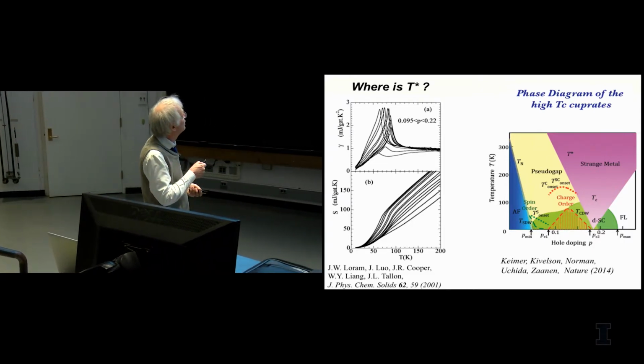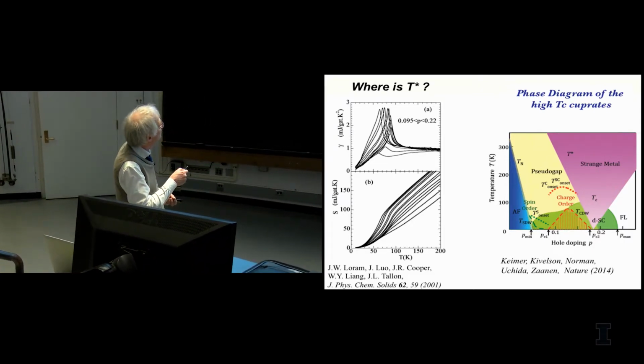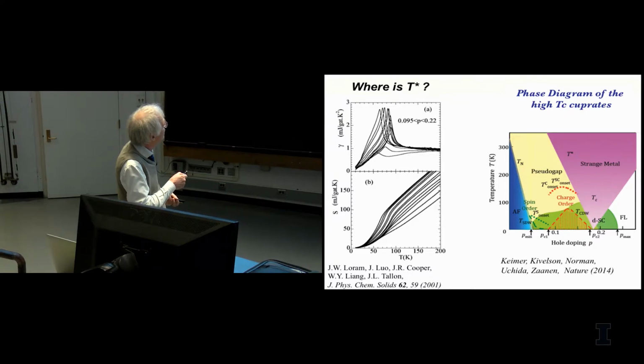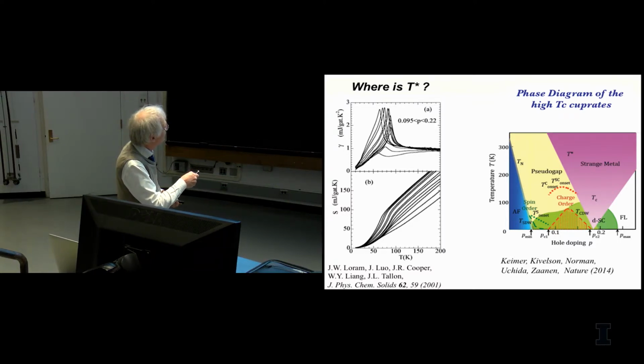And he calculated from his specific heat data shown over here the entropy as a function of temperature. This is for different dopings. This is underdoped, this is overdoped, and optimally doped. Now, entropy in a metal should just be a linear function of temperature and extrapolate to 0, which is the case for the overdoped side over here. But here, that is not the case. It doesn't extrapolate, it's actually undershooting.